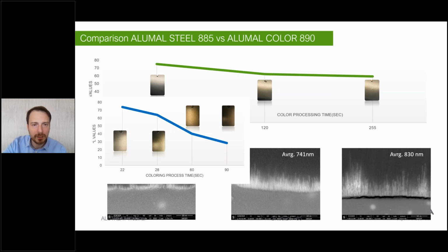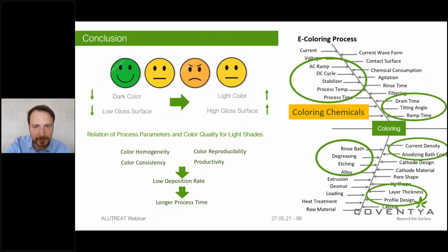And by applying this and even choosing the right electrochemical process, like the selection between nickel and tin, as you can see here, for lighter shades, the nickel-based process is much more suitable because it is, quite frankly, a more docile and less speedy process where you can have more consistent results, but it will never be possible to get to black with this system. Whereas for black, you can or you should choose the electrocoloring with tin baths.